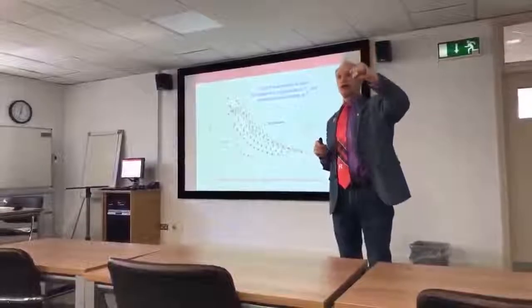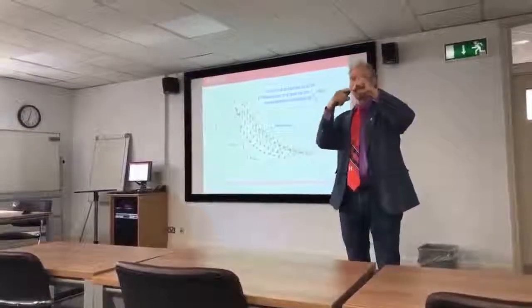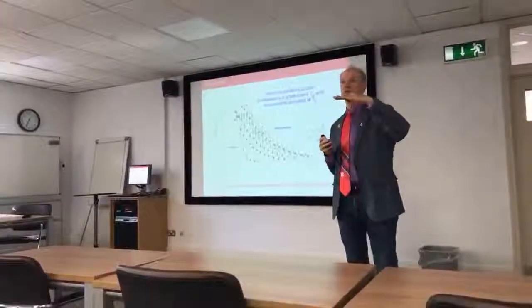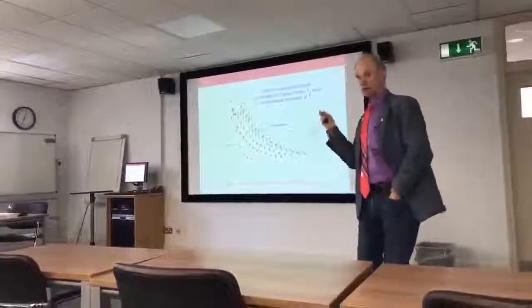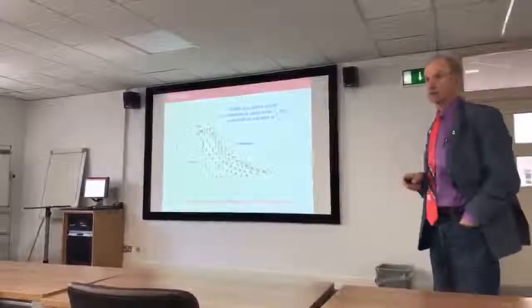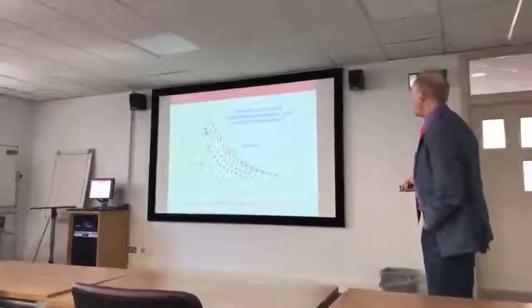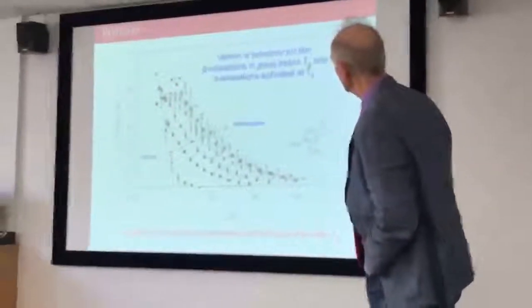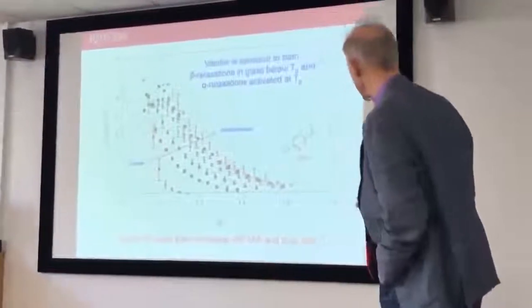I'm not saying that oxygen does not move through the matrix. I'm saying this probe does not see oxygen because it has to happen on the time scale of the excited state. Oxygen has to collide with the probe within that time, in this case about 200 milliseconds. I'll show you data from proteins, however, where the oxygen readily moves through the matrix on the time scale of the probe, and you can easily see oxygen diffusion, but not in these glassy sugars. Subtle differences: whereas riboflavin is essentially completely quenched within the glass, the vanillin is not really completely quenched, at least in the smaller sugars, until you get into the milk.